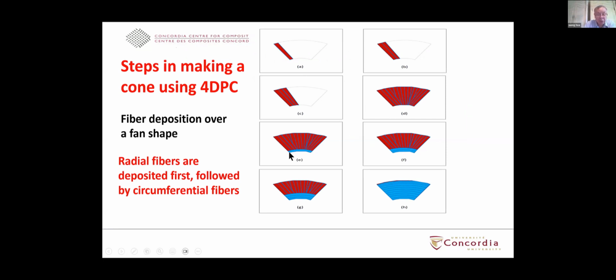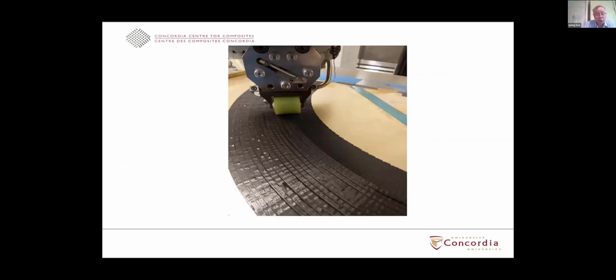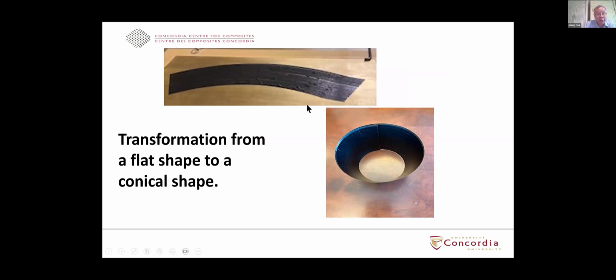And then after that, you lay down the other direction of the fiber. You have the circumferential fiber, the first strip, the second strip, third strip, and finally you have the total strip. So that means you have 2 layers, one along the radial direction, another along the circumferential direction. This shows you a photo of the layup that was made. We have already made the radial fiber, and here we are now making the circumferential direction fiber. You start with a flat laminate, and after you cure it and cool it, you obtain this cone shape. You don't need to have a mold. There is no mold in this case.